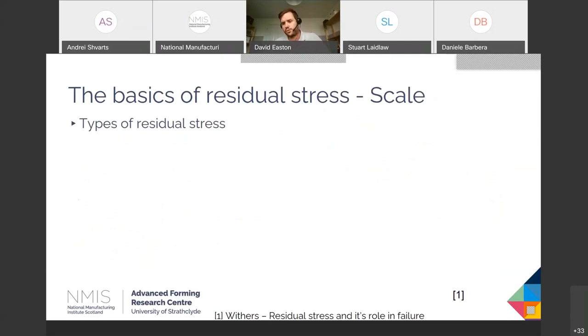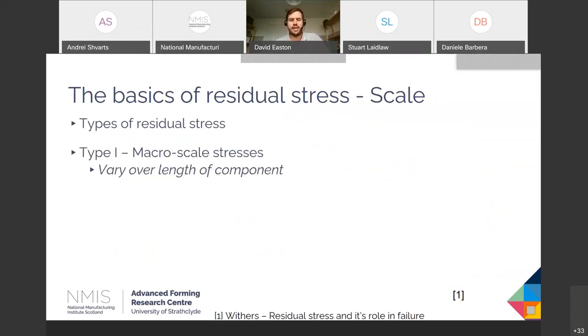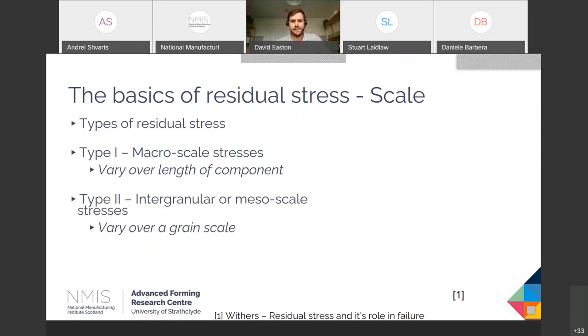Residual stresses come in all sorts of shapes and sizes and can be categorised as three predominant types. Type one being macro-scale stresses. These are the scale that we see on real manufactured components. These are big and they act over the whole length of a part. We have type two stresses. These are intergranular or mesoscale stresses. These act on a grain to grain basis. We can measure these, and these do have some impact when we're talking about real engineering situations, but less so than type one.